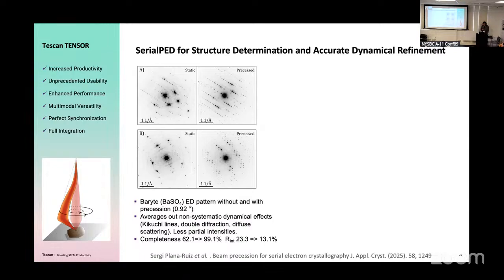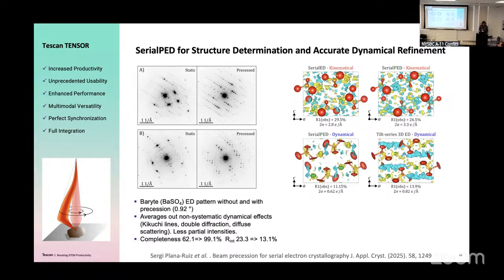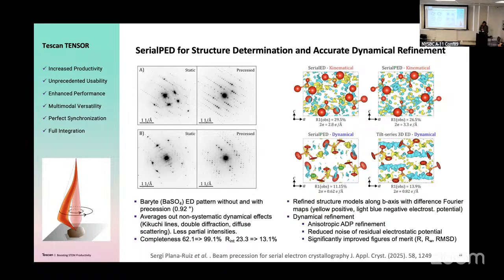And what is really cool is when they did this. This is a paper from the Jülich group, first authored by Sergi Plana-Ruiz, that I can really recommend. The completeness goes up from 62 to 99%, and the internal R factor drops from 23 to 13%. So you can really get much better data. And then the serial PED can be refined dynamically. This shows the electrostatic potential, the Fourier difference map. The noise in this map is much lower in the serial PED with the dynamical refinement. You can even do an anisotropic atomic displacement parameter refinement.